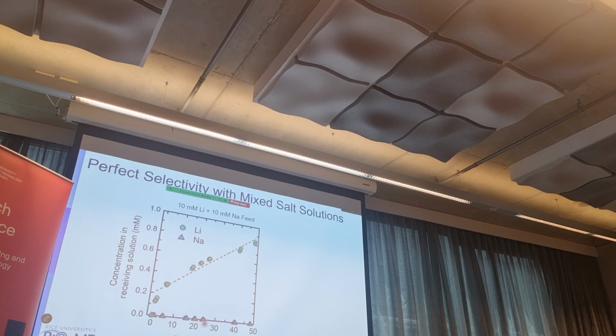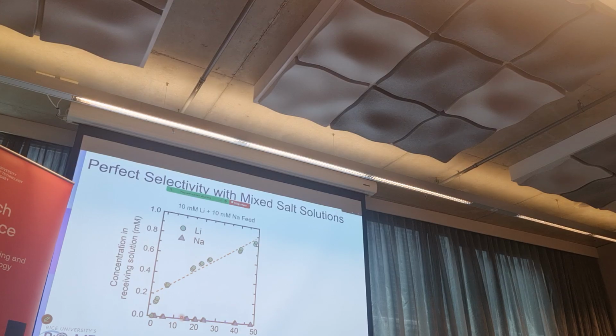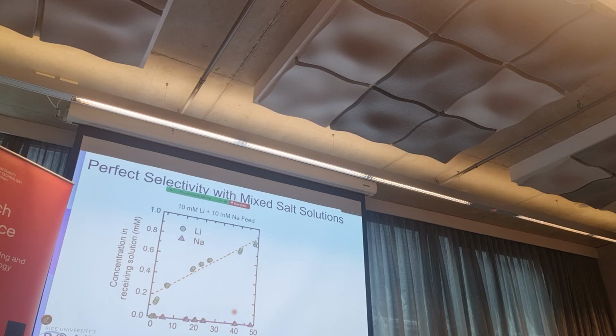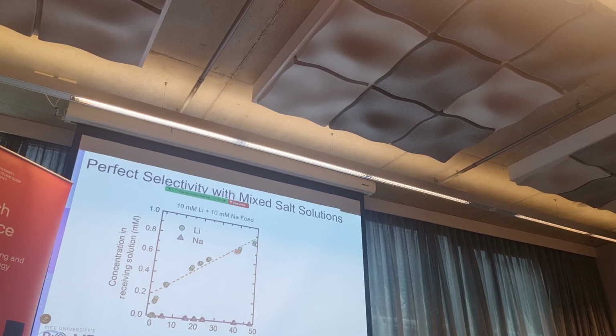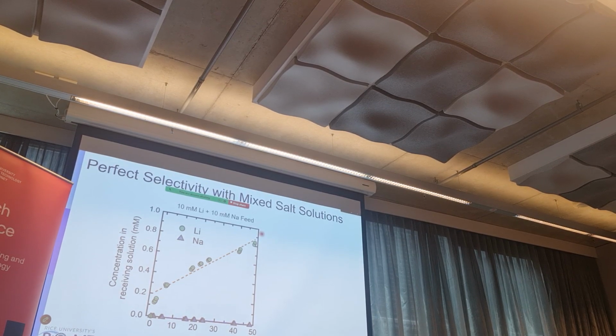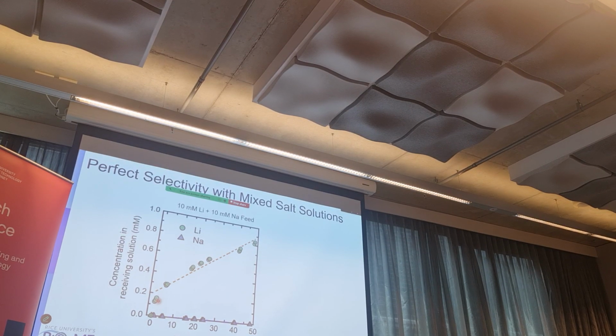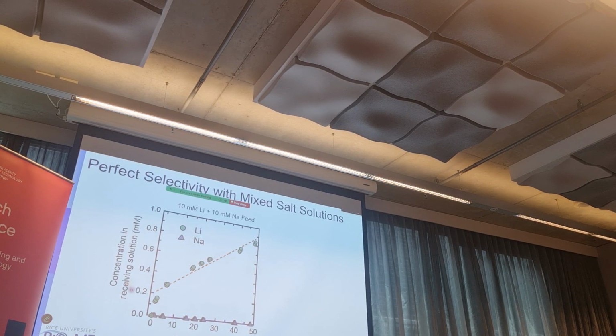Nothing comes out from the sodium side, nothing for long hours - we operated for a long time, I think at 4 volts, and we get very nice separation of lithium, as you see here. Concentration versus time shows a very fixed flux.